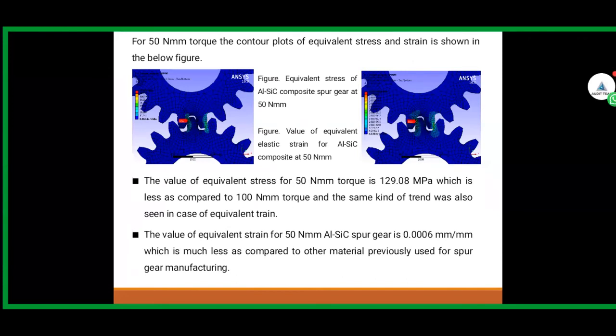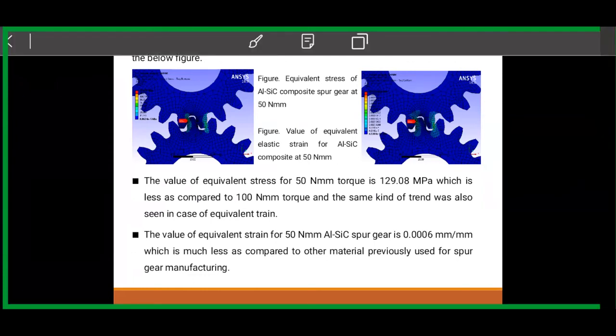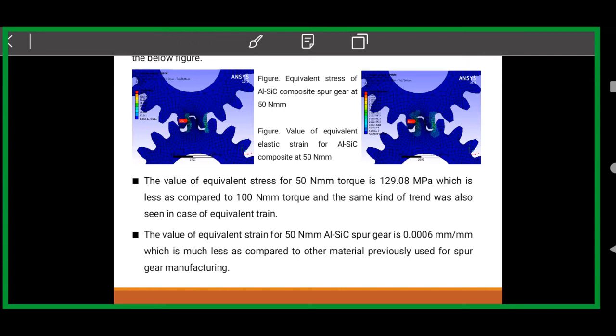Okay, this is for 50 Newton millimeter torque. Contour plots of equivalent stress and strain are shown in these figures below. The value of equivalent stress for 50 Newton millimeter torque is 129.08, which is less as compared to 100 Newton millimeter torque. The same kind of trend was also seen in the case of equivalent strain. The value of equivalent strain for the 50 Newton millimeter aluminum silicon composite spur gear is 0.0006, which is much less as compared to other materials previously used for spur gear manufacturing. I have compared these two things.